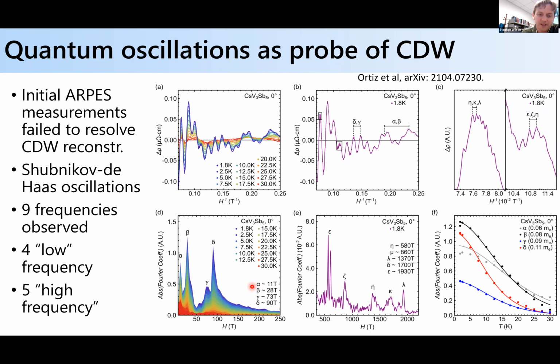In the low frequency window, we can identify four clear frequencies, which I label alpha, beta, gamma, and delta, which map to the frequencies you can eyeball here. So they're real frequencies that we can identify in the data. And the same thing with the high frequency window. In this case, we can identify five high frequencies, which again, as a consistency check, you can eyeball in the data.